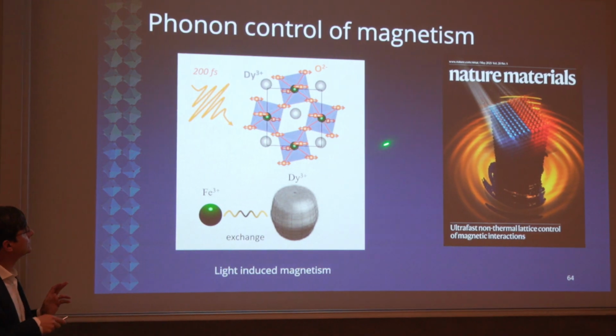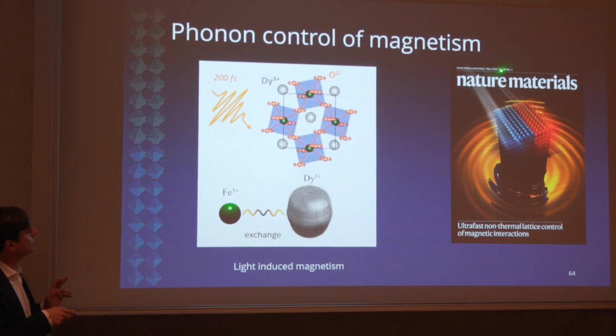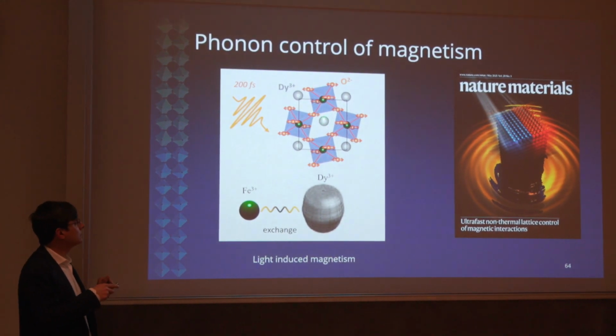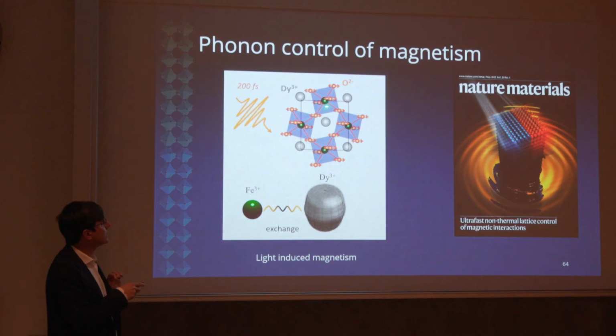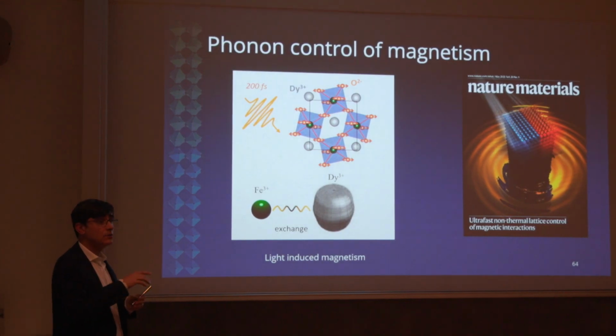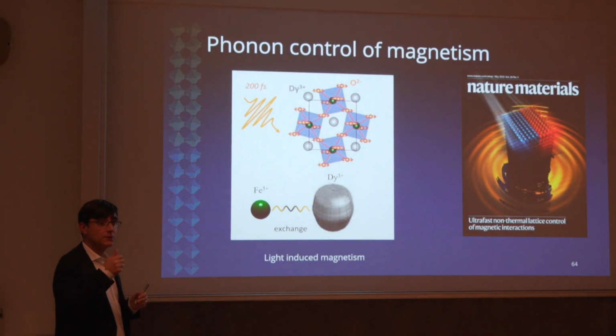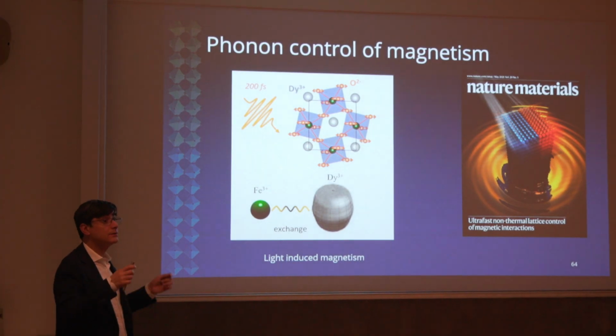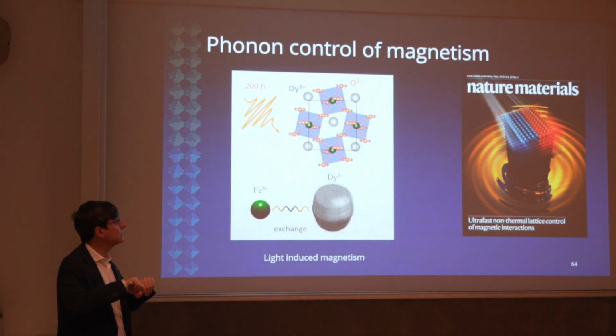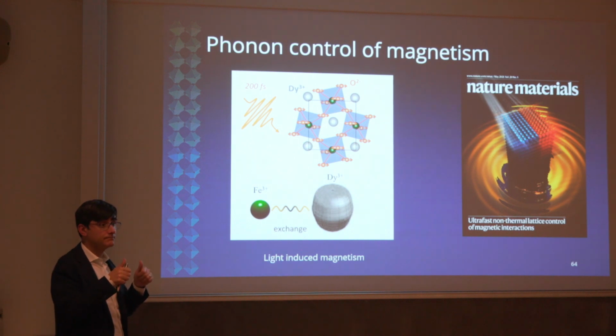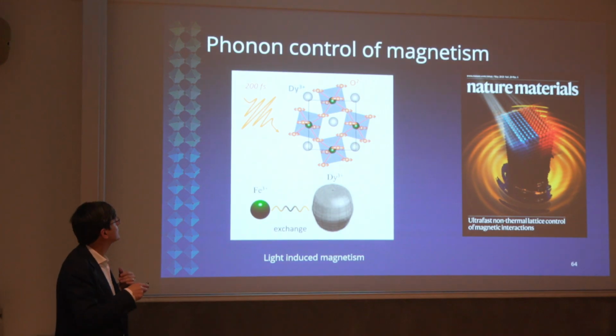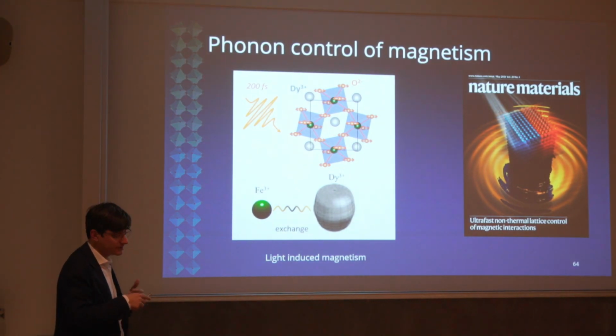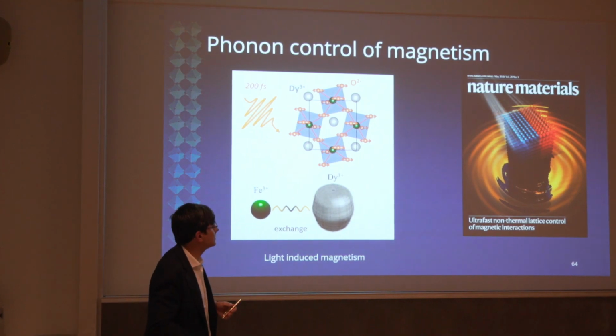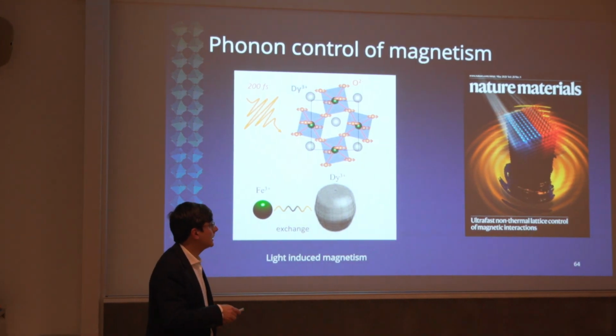Okay. And in these experiments from a few years ago, so this was 21, we demonstrated that using these laser pulses tuned in resonance with a phonon mode, we could turn a material that has no magnetization into a system that has a certain magnetization. So we could generate a transition from an antiferromagnetic state that has no net magnetization to a state in which the material develops some magnetization. So we magnetized a material by shaking its crystal lattice. Right? So we call this phono control of magnetism, and it opens interesting perspectives for non-thermal lattice control of magnetic interactions.